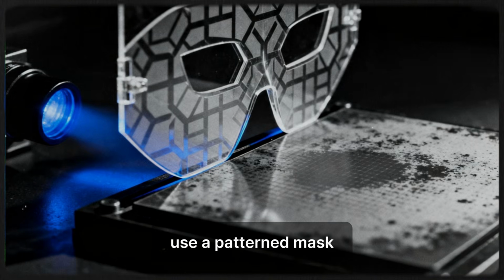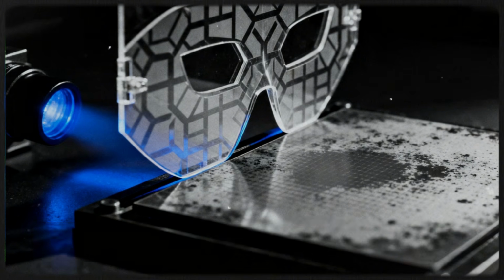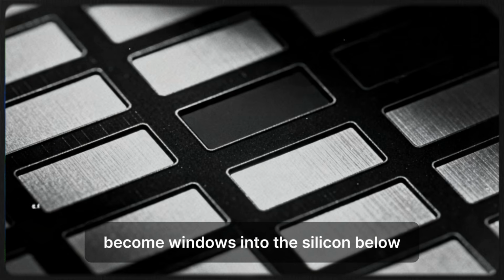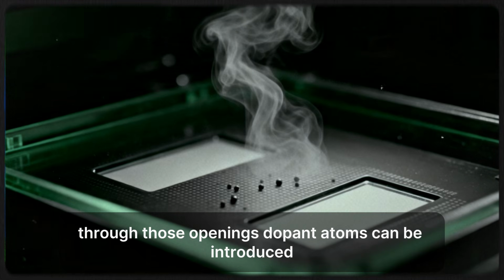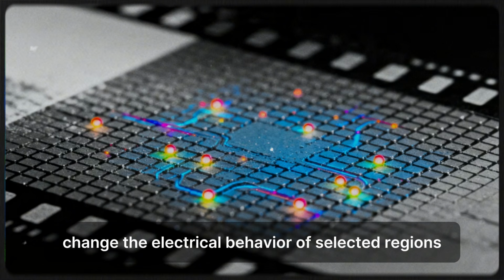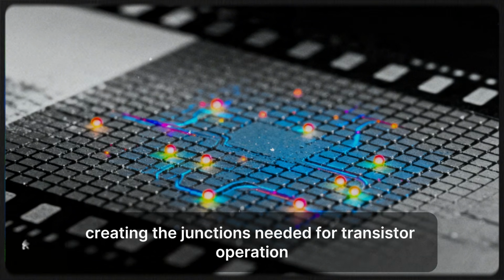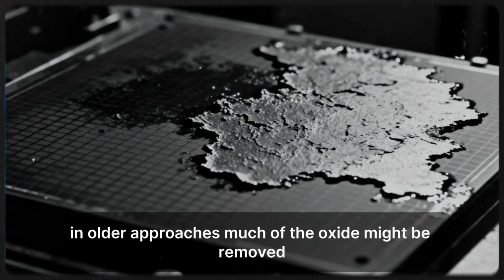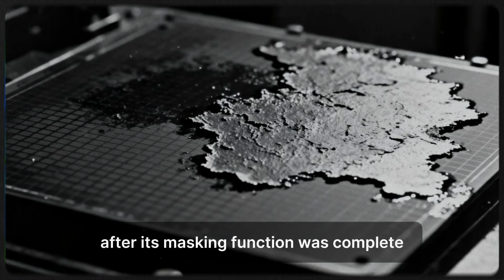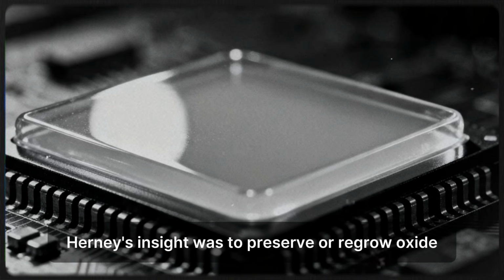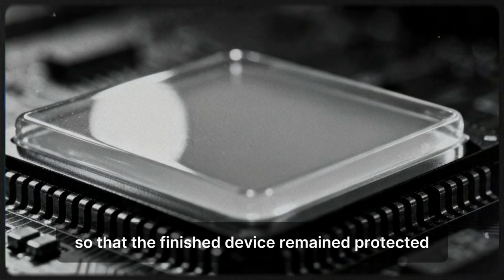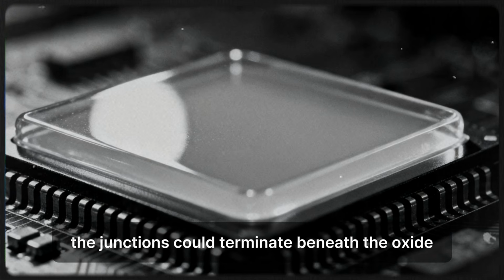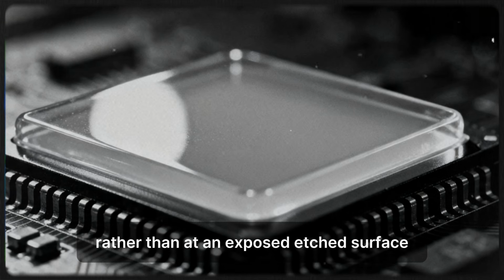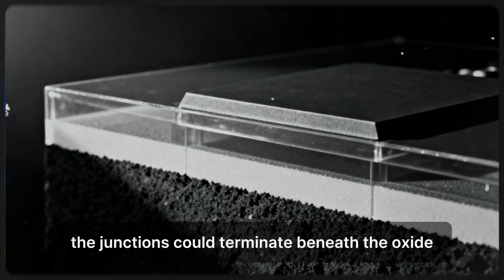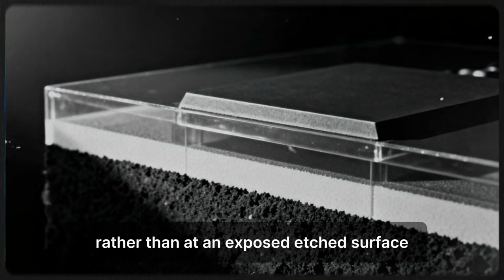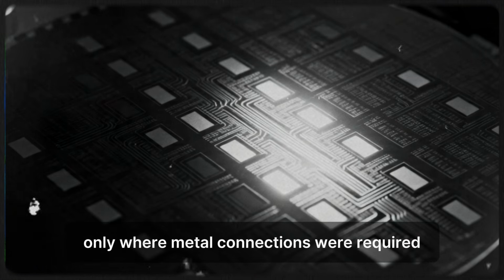Next, engineers use a patterned mask to define where parts of the oxide should be removed. The exposed regions become windows into the silicon below. Through those openings, dopant atoms can be introduced. These impurities change the electrical behavior of selected regions of the silicon, creating the junctions needed for transistor operation. In older approaches, much of the oxide might be removed after its masking function was complete. Hoerni's insight was to preserve or regrow oxide so that the finished device remained protected. The junctions could terminate beneath the oxide rather than at an exposed, etched surface. Contact holes could be opened only where metal connections were required.